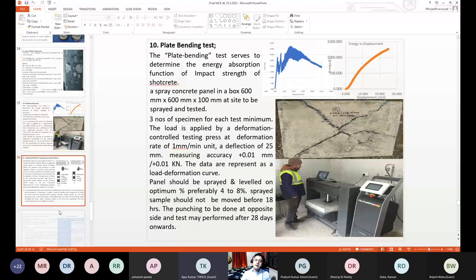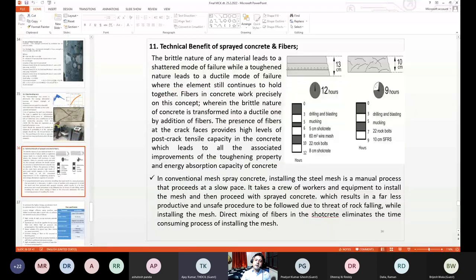The brittle nature of any material leads to a sudden mode of failure, while a toughened nature leads to a ductile mode of failure, where the element still continues to hold together. Fiber in concrete works precisely on the concept wherein the brittle nature of concrete is transformed into a ductile one by addition of fiber. The presence of fiber at the crack faces provides a high level of post-crack tensile capacity in the concrete, which leads to all the associated improvements to the toughening property and energy absorption capacity of concrete.